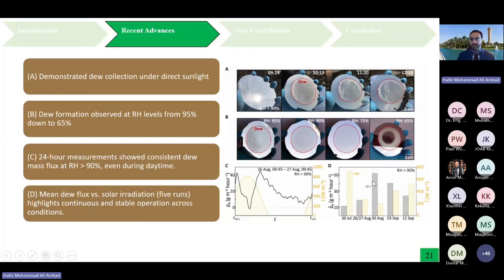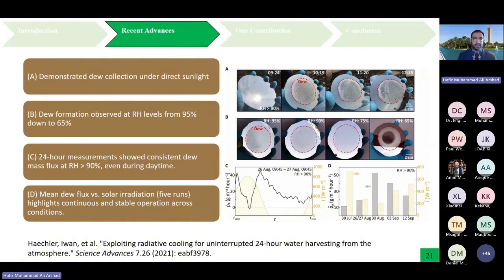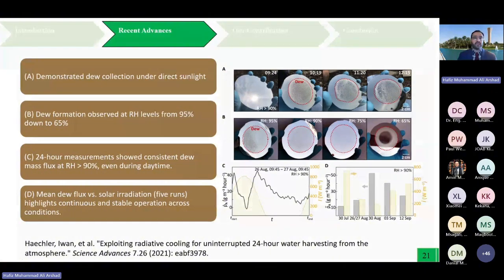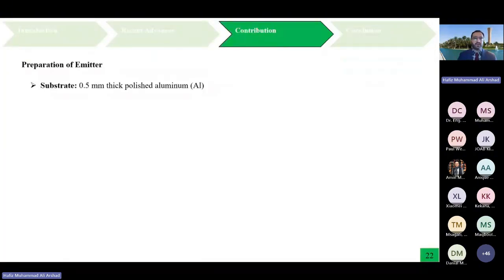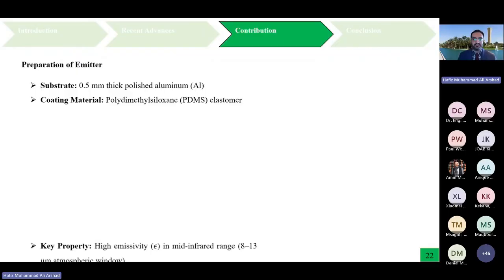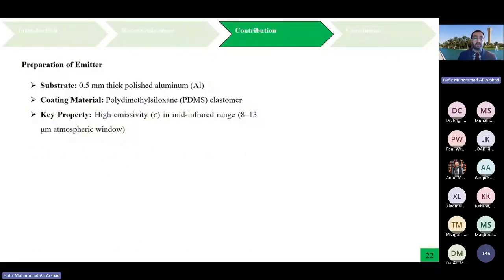Okay, so what is our contribution to air water harvesting? We made some emitters. The emitter preparation was with the help of 0.5 millimeter thick polished aluminium as a substrate, with PDMS as the coating material. And why do we use PDMS? Because it has high emissivity in the mid-infrared range, which is the 8 to 13 micrometer atmospheric window.